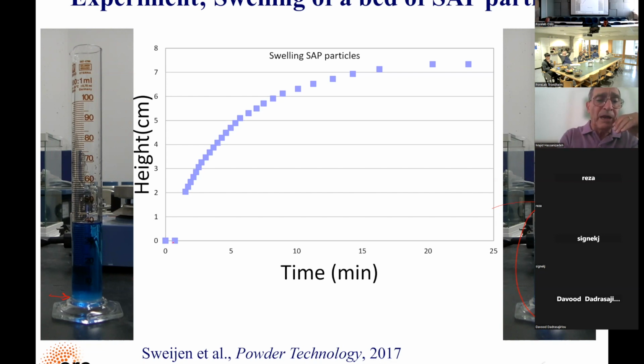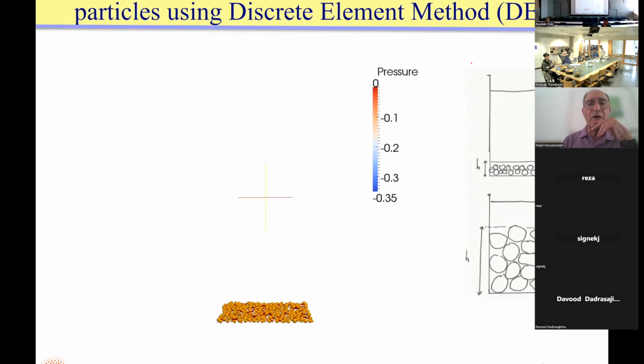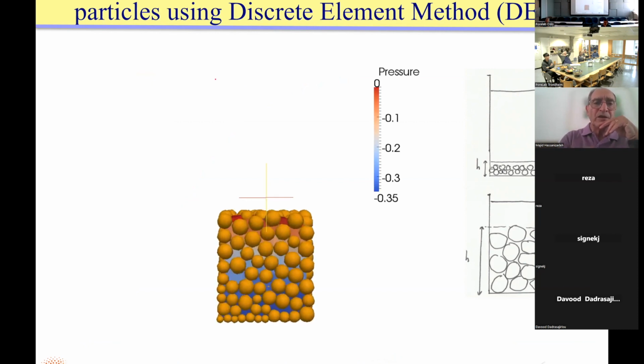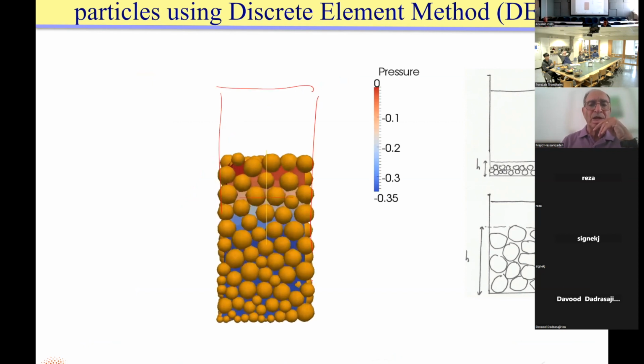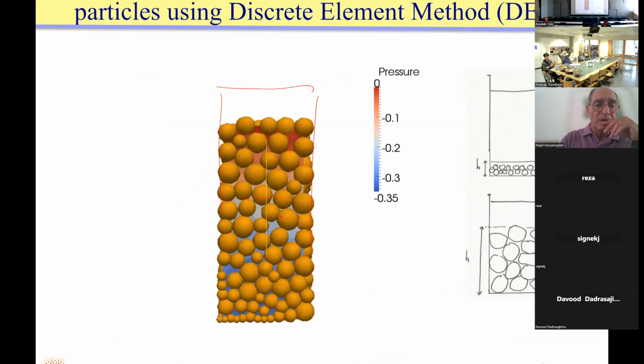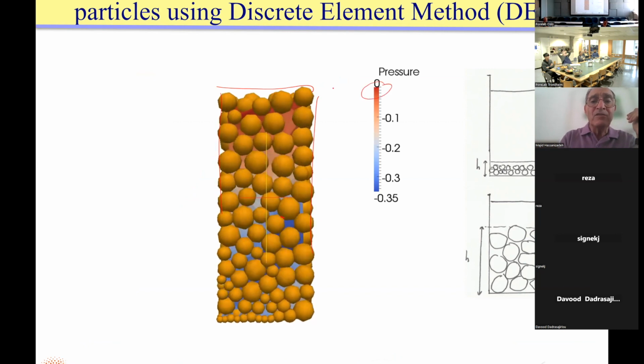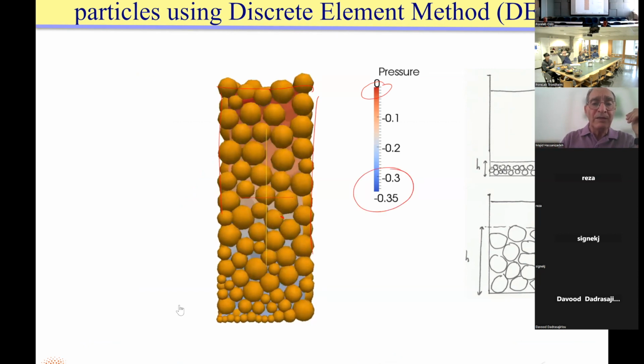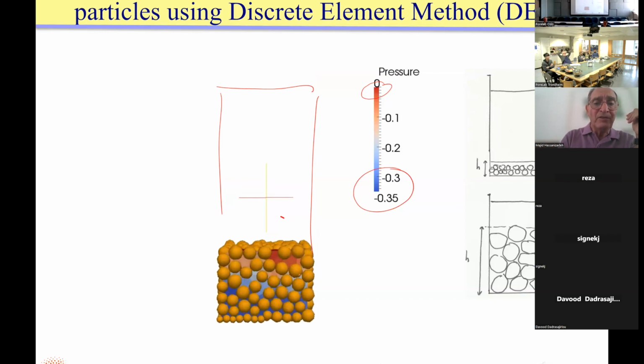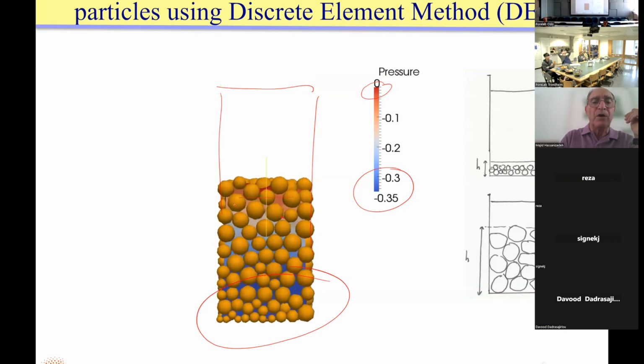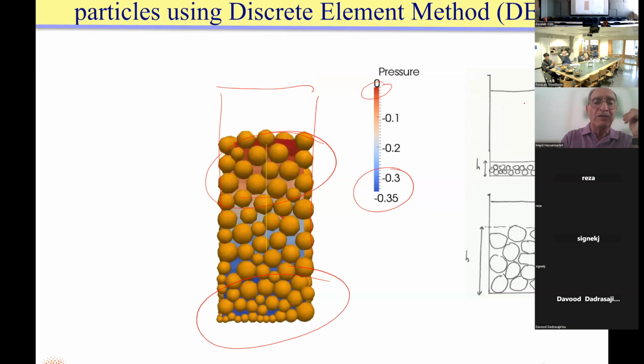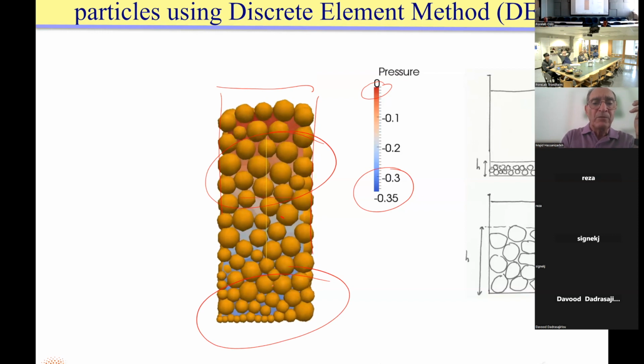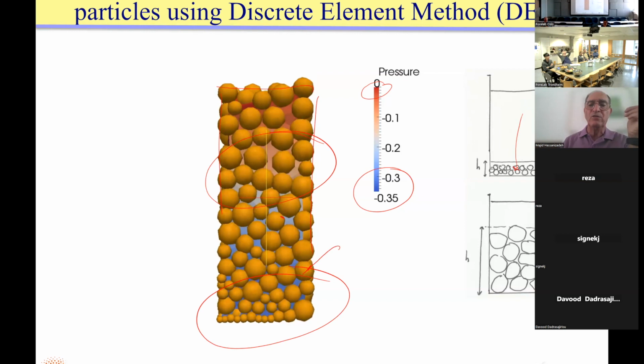Then, using a camera, we looked at the rise of the surface of the particles, and you see that plotted here as a function of time. And then we were able to simulate this process with the discrete element method, and that is shown here. The particles are growing. Water is basically up to here, so it's growing into water. And what is interesting, let me stop it. You see that red is higher pressure than blue. And what you see here is that the pressure, instead of being higher at the bottom, is lower at the bottom and higher in the upper area, because the sucking of water by these particles will create a suction and will move water down into that bed of particles.